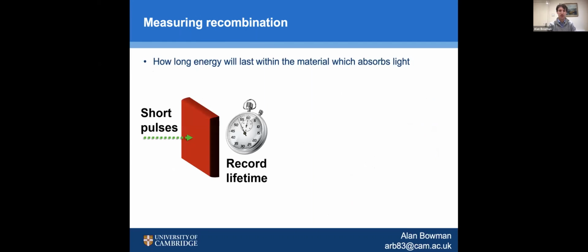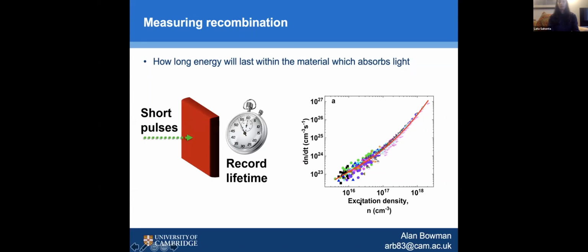To measure recombination, I won't go into that in much detail, but effectively we're measuring how long energy lasts within the material. And the way we do that is we fire short laser pulses at the material, and then we time how long energy lasts in the material following those short pulses. We get something like this coming out that I won't go into in any detail. Effectively, this is the number of electrons in the material on the bottom, and then this is how quickly the electrons are being lost on the y-axis.